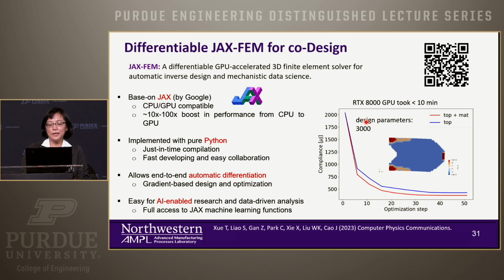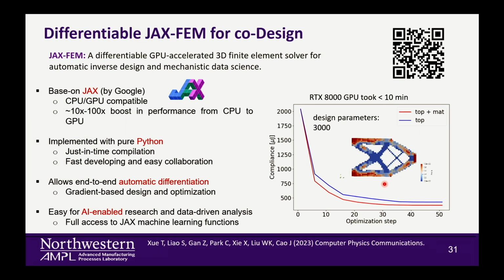If you look at the barcode, it's open source. You can download it. And because it can give you the sensitivity kind of for free, you can use it, as I mentioned, for topology optimization as well. The example that you see right here is a very typical compliance optimization, right? What we are optimizing here is not just the topology. You see the color bar. The color bar also gives you a range of the yield stress difference. So some of the material could be softer, some of the material could be stronger.